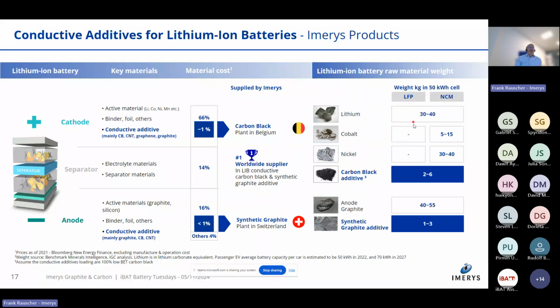kg of those materials go into a 50 kilowatt hour cell. And you see for carbon additive in a 50 kilowatt hour cell, depending on the amount of carbon black that you add to your cathode formulation, it's 2 to 6 kg, but not more, right? For the other elements, it's significantly more. We don't do anything on the separator side.